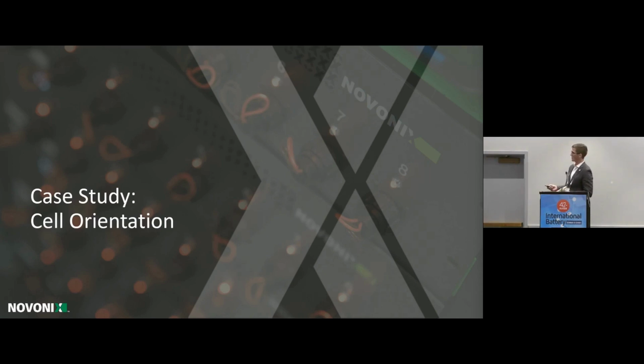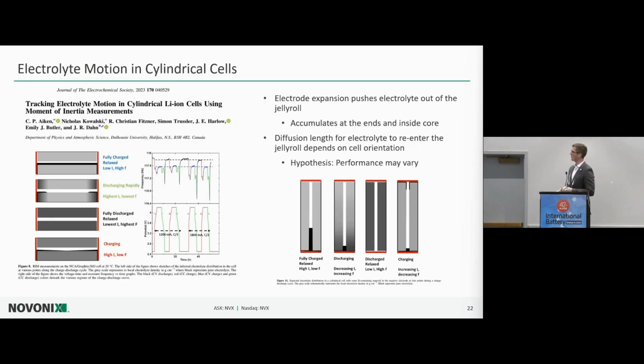So this was inspired by some work done in the Don lab where they were looking at electrolyte pumping, and Jeff gave a nice talk where he mentioned this phenomena the other day. And what they realized is that there was a difference between what happens when you cycle cells oriented vertically versus horizontally. And this could be related to how the electrolyte moves in and out of the cell when the cell is breathing, say, during charge and discharge. So what we wanted to figure out is, can we use UHPC to detect that this is happening? And how quickly can we do that?